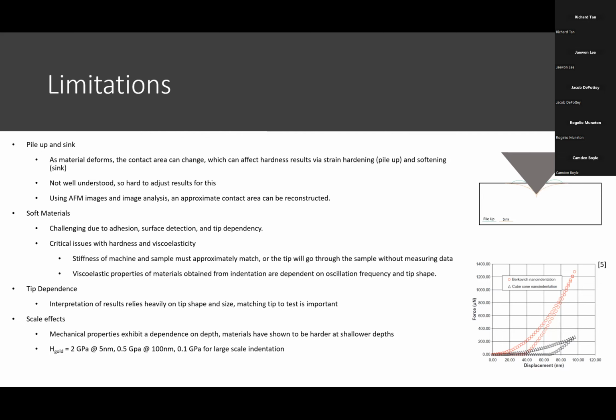The last limitation would be scale effects. Mechanical properties exhibit a dependence on depth - materials have shown to be harder at shallower depths. If you're nanoindenting, you're only going maybe 100 nanometers into a surface, so you have to keep in mind that those results may not be the same you'd get from a shallower or larger depth. A good example: when you measure the hardness of gold at 5 nanometer indentation depth, you get a hardness of 2 gigapascals. At 100 nanometers, you get 0.5 gigapascals. And for large scale indentation, 0.1 gigapascals. So just keep that in mind.